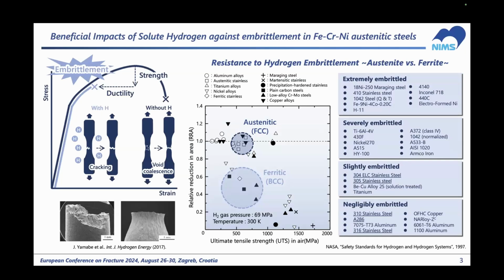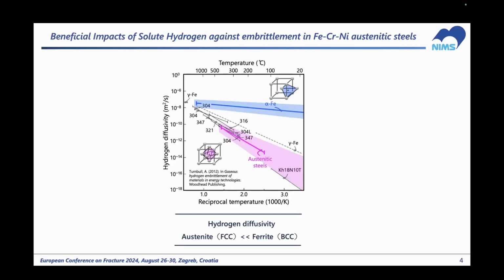And here I show the very famous NASA database in which the hydrogen embrittlement resistance of various types of metallic materials are compared in gaseous hydrogen. In this database, almost all types of austenitic stainless steels are classified as just slightly or negligibly embrittled materials, in contrast to the ferritic or martensitic steels with BCC crystal structures. One reason for such excellent hydrogen embrittlement resistance is, of course, the slow diffusivity of hydrogen in austenite, which is almost 4 to 5 orders of magnitude smaller than the diffusivity in ferrite, which can retard the accumulation of hydrogen into fracture nucleation sites, such as grain boundaries or crack tip phase boundaries.